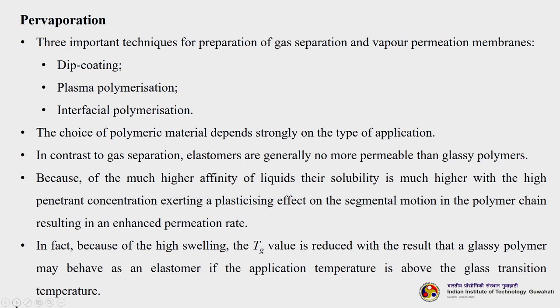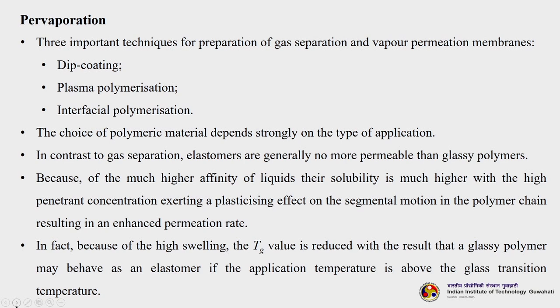The choice of polymeric material depends strongly on the type of application - when removing organic compounds, a different type of polymer material has to be chosen compared to other separations. In contrast to gas separation, elastomers are generally no more permeable than glassy polymers, because of the much higher affinity of liquids. Their solubility is much higher, with the high penetrant concentration exerting a plasticizing effect on segmental motion in the polymer chain, resulting in enhanced permeation rate. Because of the high swelling, the Tg value is reduced, and a glassy polymer may behave as an elastomer.